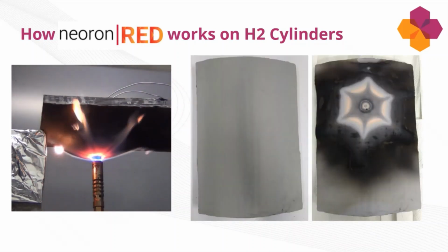And on the right side, you can see before and after. Before on the left side, of course, and on the right side, you can see that kind of spider web figure coming out after the burn. This is a 30-minute burn, and well, the video started to get boring because nothing really happens after the stabilization, after the ceramification, after the expansion. It's pretty boring to watch. We are not going to watch half an hour of that. We just skip to the end.